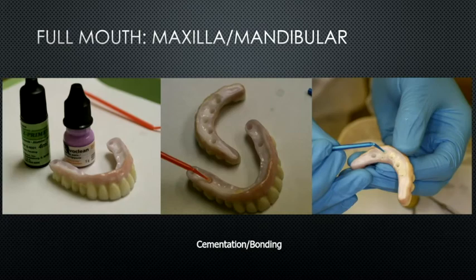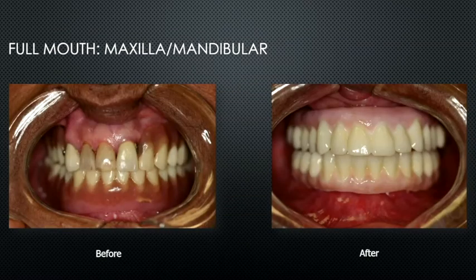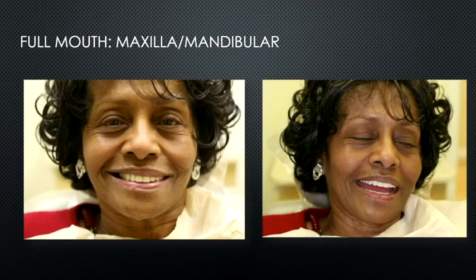Oh, by the way, I want to share this with you. This is a decontaminant. When you're trying to cement ceramic to ceramic, or ceramics in general, you want to use IvoClean because it removes all the contamination from the zirconia. Zirconia has free ends, and it tends to attract phosphates and things like that, which occupy the free bonds. So when you bond, the bond is weak. So you always want to do a clean and an etch so that you get good adhesion. So we took her from here to there, and that's what she looked like at the end of the treatment.